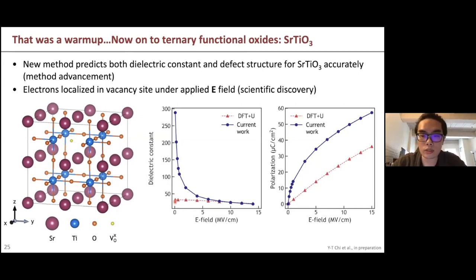And here I'm just showing some of the work that we get. We can get this nonlinear relationship of the polarization at low field. This gives us a high dielectric constant of STO. And then you can see when you apply the field higher and higher, the dielectric constant actually drops very fast. This is also already verified by experiment: in this kind of material, the ion movement will be impeded when you apply the electric field higher and higher. Soon after, the dielectric constant will go down to around 20s or 30s.